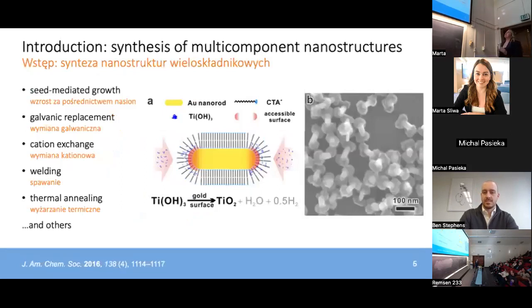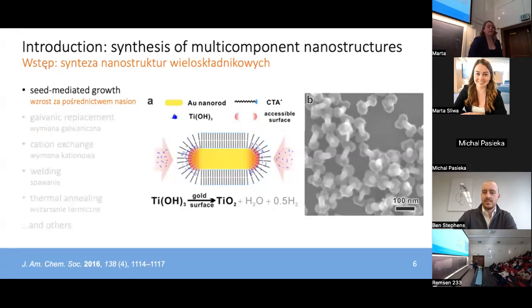So there are a number of different ways that we can make these multi-component nanoparticles. We can grow or deposit a secondary material on an existing particle in a process called seed-mediated growth. We can replace some parts of an existing particle in processes like galvanic replacement or cation exchange reactions. We can chemically weld 2 or more particles together to form a larger structure. And we can also heat atomic precursors or collections of nanoparticles and thermally anneal them to form these multi-component nanostructures. With these examples only reflecting a few of the different synthetic techniques out there.